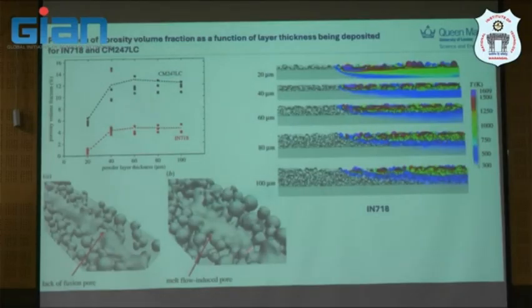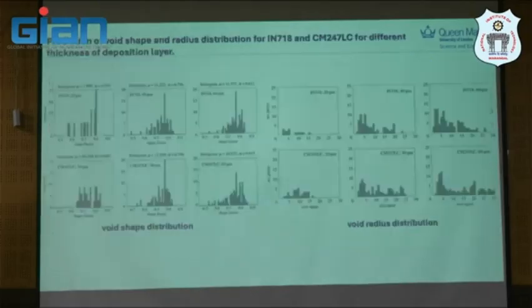What we do is we actually try to classify from simulation. I think this is my work. Lack of fusion or keyhole porosity, and we try to map across the composition as a function of process parameter. In this case, it's surface, that is a layer thickness. But what we did, and this is something I want to suggest to the community, is we predict the distribution of that.